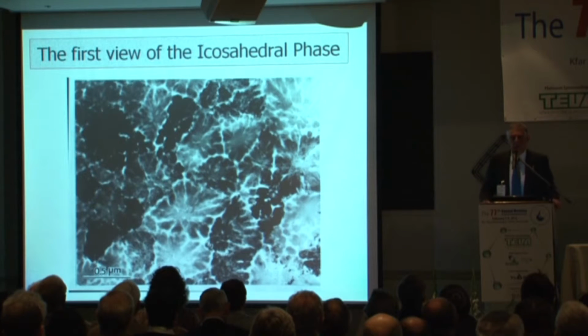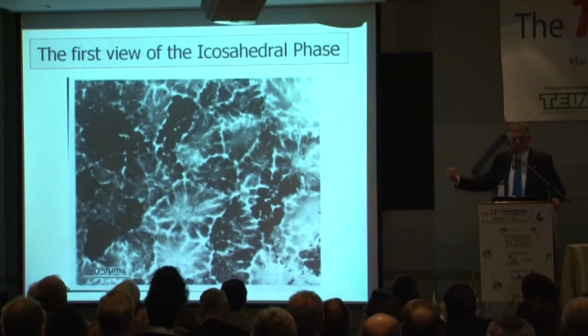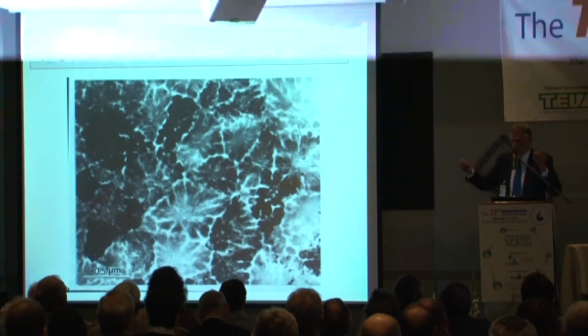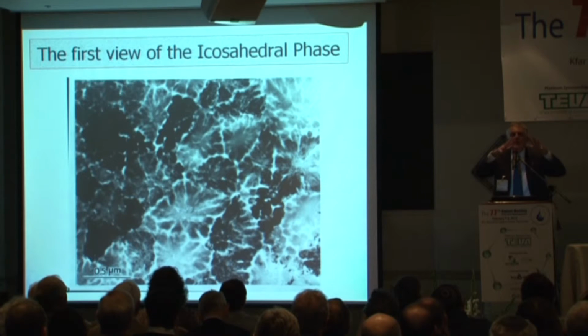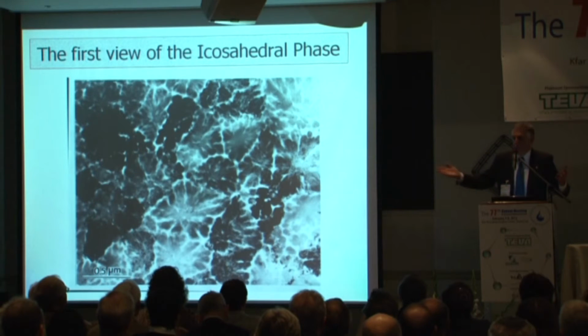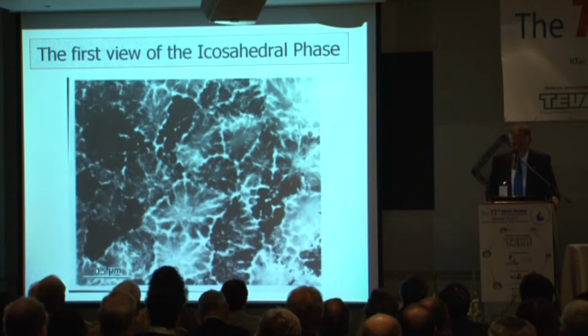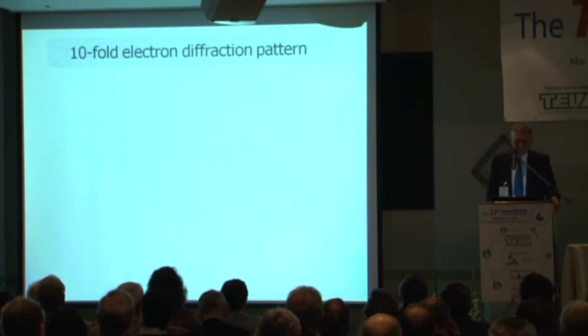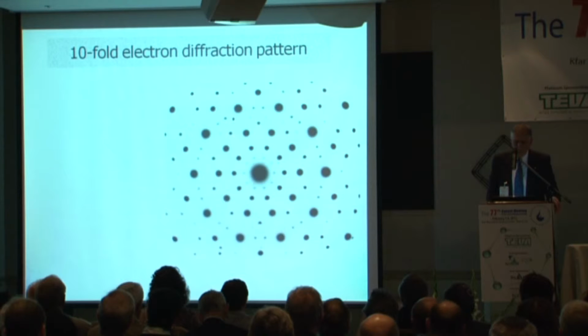What it means to the electron microscopy is, because this is a bright field image, it means that crystal, that grain as we call it, diffracts heavily. So most of the intensity goes out from the image, and through the objective aperture only the transmitted beam goes, and the intensity of that transmitted beam is so weak that nothing goes through because of the diffraction. And I said, oh, wow, let's look at the diffraction pattern. And this is the diffraction pattern. This is the actual picture, the first picture.